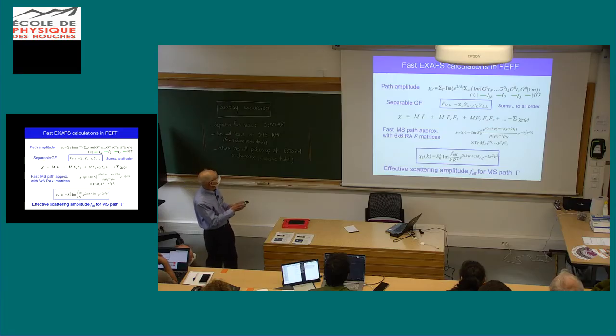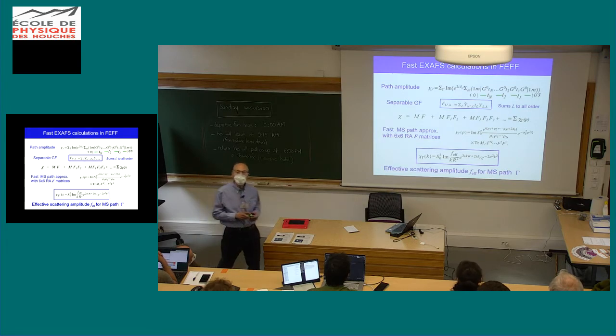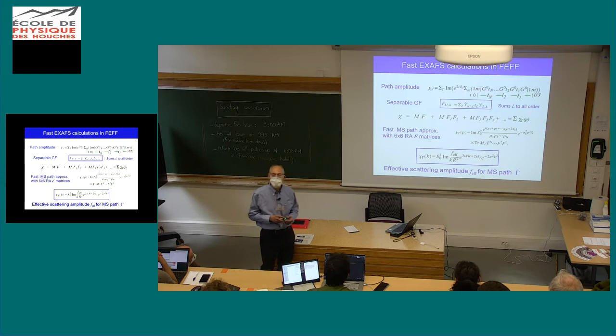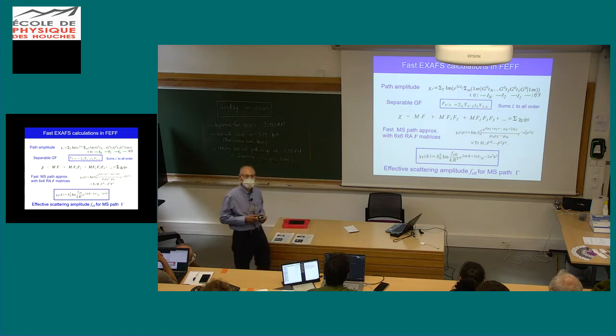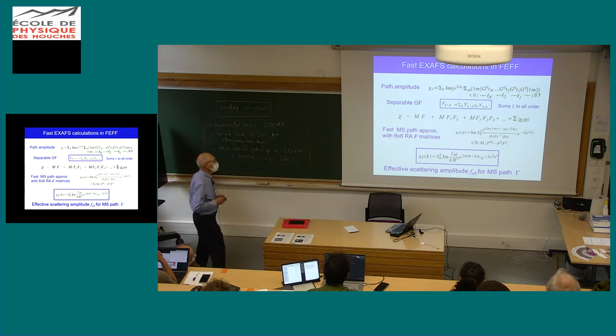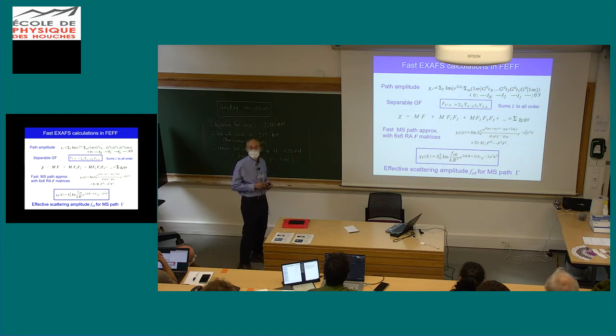This is our separable matrix. And the cool thing about this separable matrix is that now you can sum all the L's at one site all the way up. Just like in the expansion for the scattering amplitude in potential scattering. You remember the equation, sum t to the L PL cosine theta or something like that. You sum over all L's. We go up to L equals 25. That's about 1,000 electron volts or 1,500 electron volts.